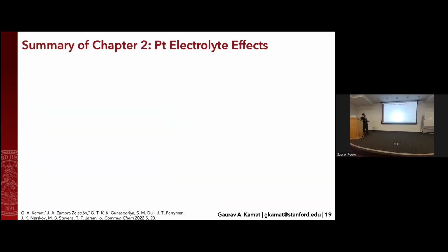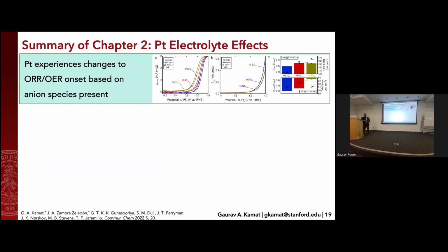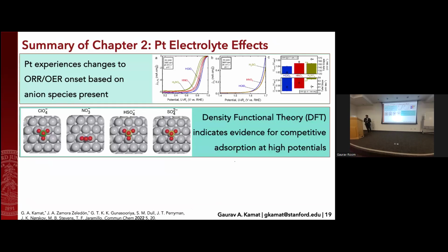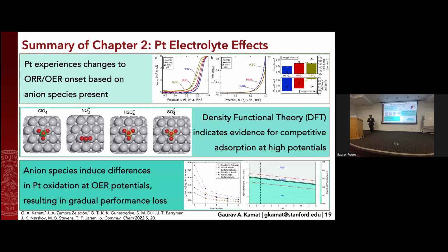So as a quick summary of this chapter, we saw that platinum experiences changes in the oxygen-based reaction, specifically based on the anion present. We saw that density functional theory can indicate evidence for competitive adsorption in conjunction with the experimental data we collected, and also that anion species can induce different rates of platinum oxidation under oxygen evolution potentials.